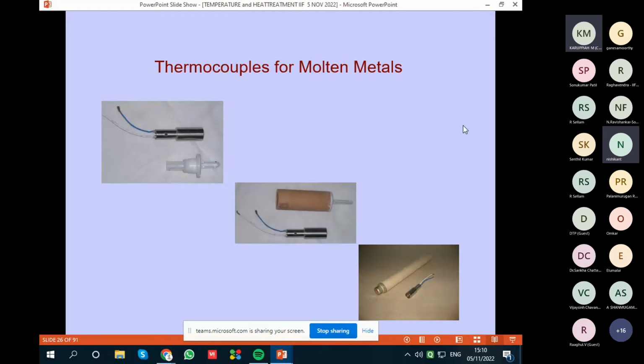The tip on the right-hand side bottom is a carbon tube tip, which you can dip in the molten metal. And different lengths are available, 300, 400, 600 carbon tubes. And the measurement is done quickly, in about 2, 3, 4 seconds. And the one on the left-hand side top is another thermocouple, which is fitted in a cardboard tube, just like the multi-dip, but it comes with a cardboard tube. That is also very popular.